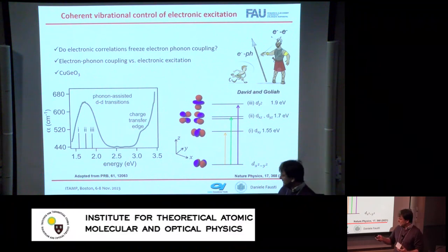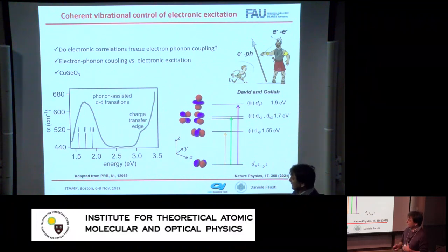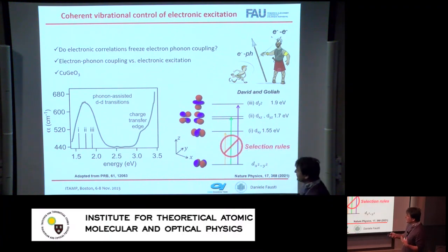To do this, we choose the system that is one of the family of the cuprates, but is peculiar because it has the absorption which is characterized by DD on-site transition, and this DD on-site transition should be forbidden by selection rule because the system has inversion symmetry, but they are actually visible in the optical absorption. And people describe this situation as phonon-assisted transition. I spare you the model, but essentially every time a photon is absorbed, there is a phonon that participates into this process and breaks the symmetry.